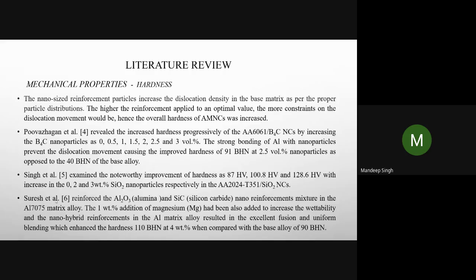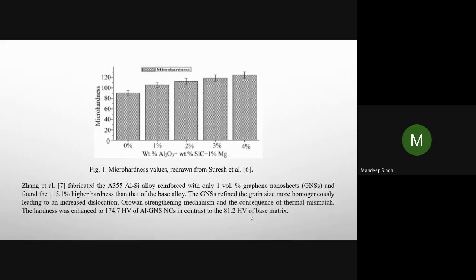Then next we have Suresh and others, who reinforced the alumina and silicon carbide nano reinforcement mixture in the AA7075 matrix alloy. The 1 weight percent addition of magnesium has been added to increase the wettability of the nano hybrid reinforcements in the aluminum matrix alloy, which resulted in excellent fusion and uniform blending and increased the hardness to 110 Brinell hardness at 4 weight percent when compared with the base alloy of 90 Brinell hardness number. So here is a figure which explains itself: as the weight percentage of nano reinforcement is increasing, the overall hardness is also increasing.